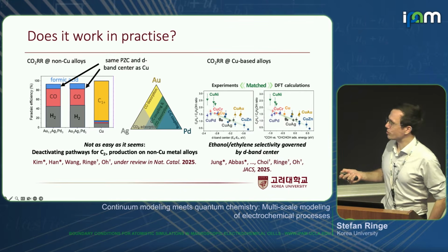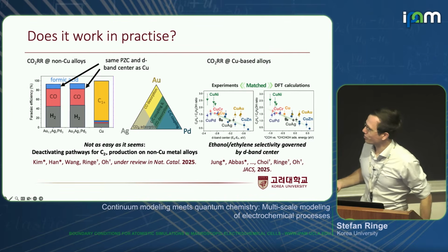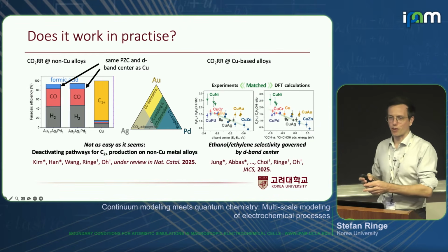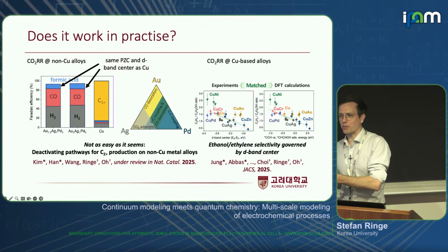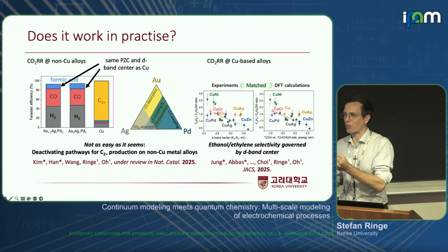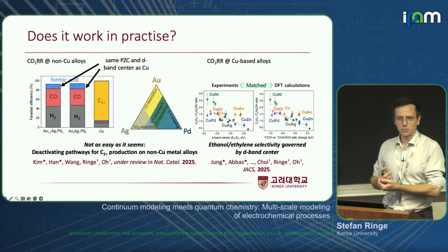Now we can try to introduce palladium, but pure palladium has the problem that it binds CO too strongly, so the CO coupling step will be very difficult. And then in the middle, we usually also have CO desorbing, because CO can just jump to the next site and desorb. And CC coupling could be limiting as well. From running a lot of different configurations, we found that one of these steps always happens, so it's not possible to combine these alloys in a way that reproduces copper. Copper is still kind of unique in forming these C2 plus products.